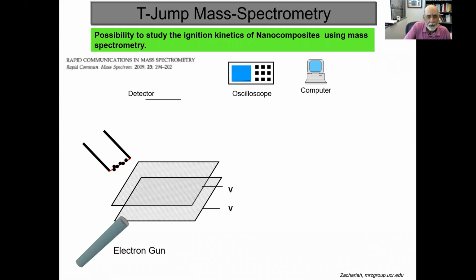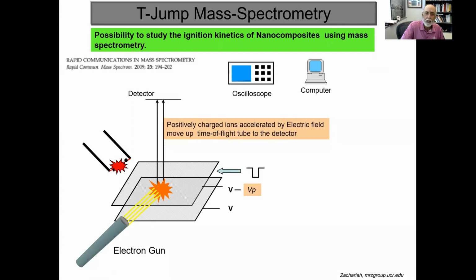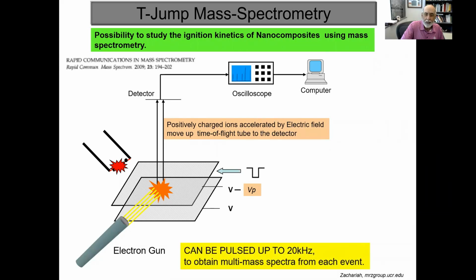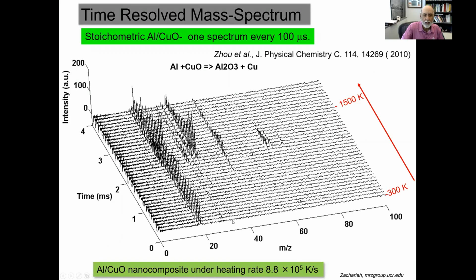Now, if we embed this into a mass spectrometer, what you can do is heat the wire, and material comes off the wire. You can then ionize that with electrons and do time of flight mass spectrometry to enable you to get a mass spectrum at a high rate. So we can pulse this process at around 20,000 hertz so that you can get multiple spectra.